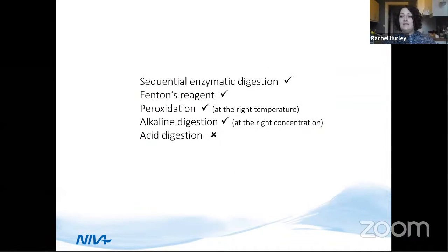From our testing at NIVA and also in the wider literature, we found that enzymatic digestion and Fenton's reagent are both safe for particles, at least down to 50 micron in size. The use of hydrogen peroxide or alkaline solutions is also considered safe, so long as safe temperatures and concentrations are observed. Acid digestion is not safe for particles, as acids can destroy a wide range of different particle types.